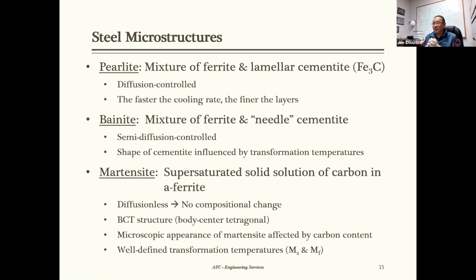Martensite is completely different. Martensite is a supersaturated solid solution, so there's no precipitate and no cementite. Basically this is a diffusionless constituent, and the structure is slightly different, called body-centered tetragonal. If we do a tempering, forming tempered martensite, the microstructure is a mixture of ferrite with tiny cementite. If you add alloy in there, then you form a lot of different precipitates.